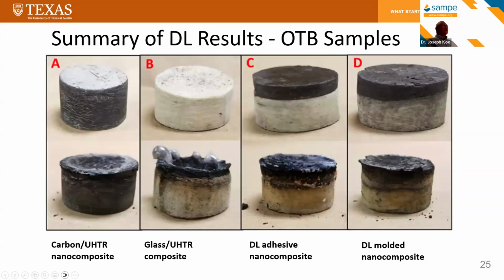Okay, this is a summary of what my students have done comparing the carbon UHTR nanocomposite. On top, you can see the material before it was tested and after it was tested. We can see the glass is melting on the surface. Carbon is not. And we examine how we bond these two different layers of material, one the ablative material and one the insulating material.